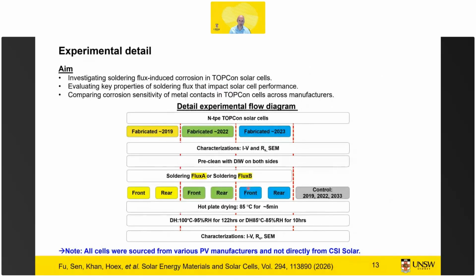So these were not randomly selected. These were industry-relevant soldering fluxes. And then we exposed the solar cells. So these are not modules. We exposed the solar cells to the soldering fluxes on the front and the rear. And then we first dried it, and then we did cell level damp heat testing. But again, this is relatively quick, as I will show you later. And this was work done directly in collaboration with CSI Solar, but the cells were not made by CSI Solar.